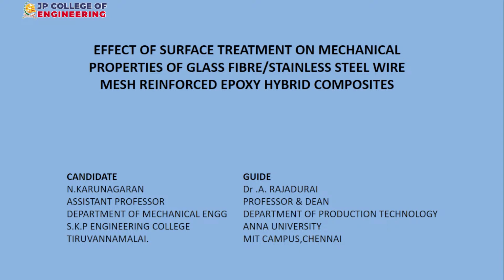So this is on preparing a hybrid composite. Hybrid means by adding two or more reinforcements. In this case, in addition to the glass fiber, which sometimes breaks and will not have adequate impact resistance, we thought we can have a metal mesh also, a very fine mesh. You cannot put a coarse mesh, which will be counterproductive and will not bond well. So we put a very fine SS mesh in the middle layer. We made a multi-layered composite. We checked the low velocity impact behavior. So this was the idea.